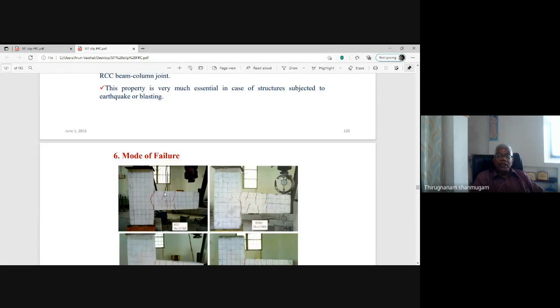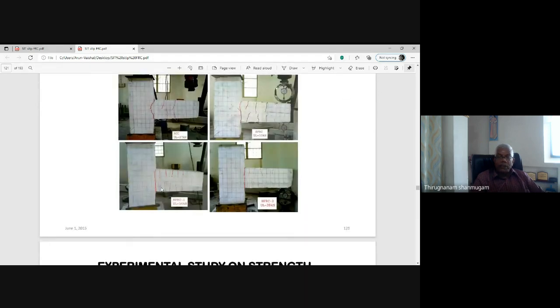For RCC, sudden failure of the beam column joint is possible because the plastic hinge is formed at the beam column junctions and the beam fails. But here, instead of single cracks, a series of hair cracks are visible throughout the beam length, and it will take more and more load to develop the full plastic hinge mechanism. For HFRC also, there are a number of series of flexural cracks, but the ultimate failure is similar to SFRC.